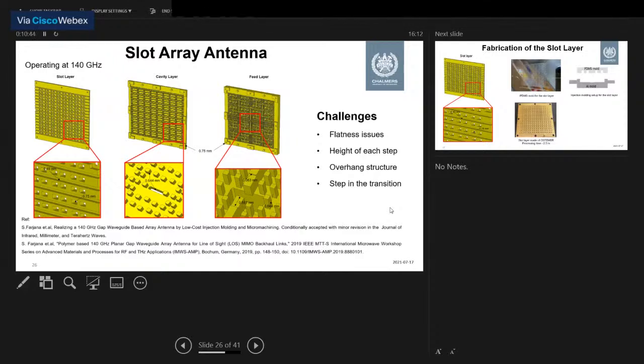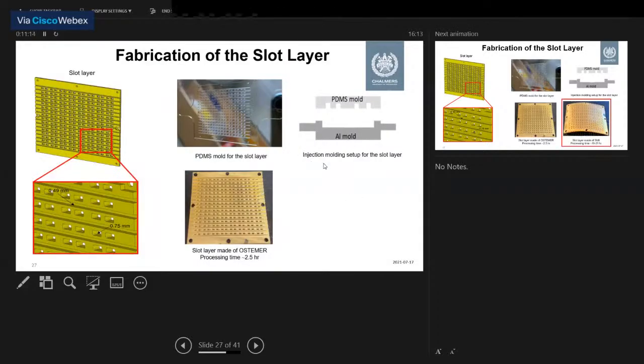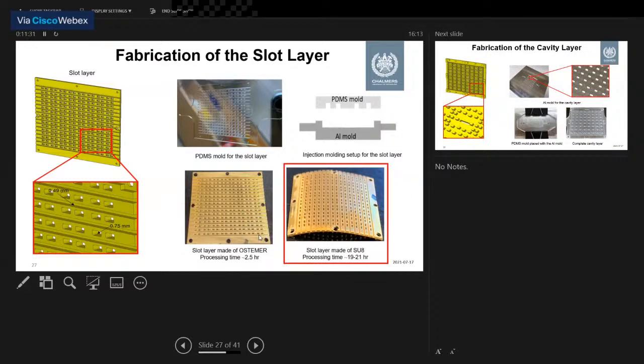So the issue in fabricating this antenna is flatness, because it's a very thick structure, with height of each step and an overhang structure. You can see here we need an overhang structure, which is very complicated to get with silicon micromachining or other photoresist based methods. And this small step in the transition is also very complicated to achieve by other fabrication methods. But when we fabricate the slot layer, we can easily transfer the slot layer in a SUEX master, and then transfer it to the mold. And then we have this OSTEMER slot layer.